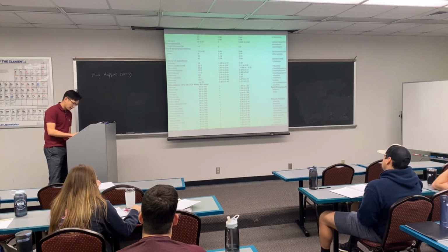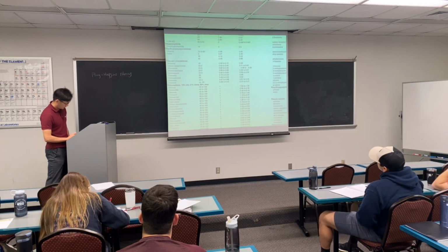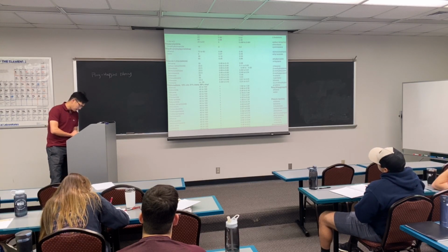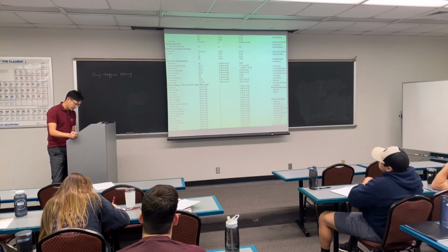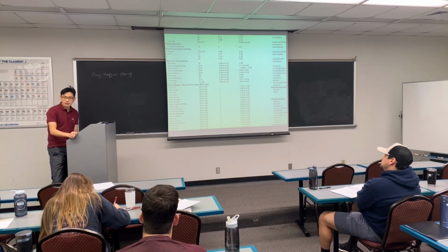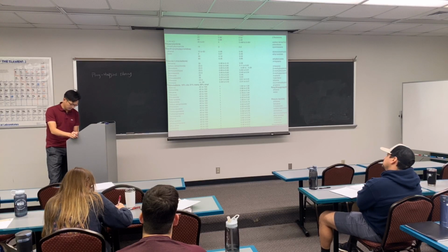If we look at the specific values here, you can see for polybutadiene with a variety of solvents, the chi parameter is usually larger than 0. You have values from about 0.3 up to 0.6.